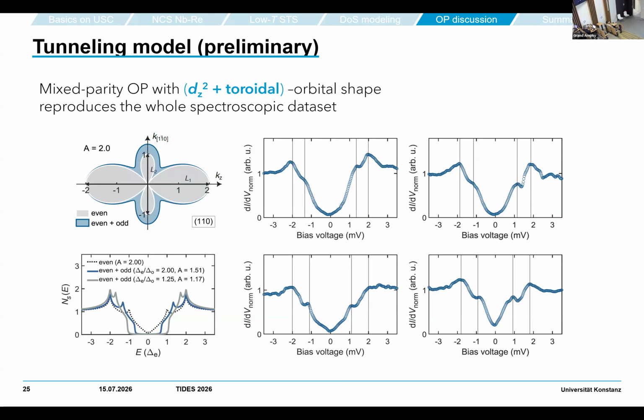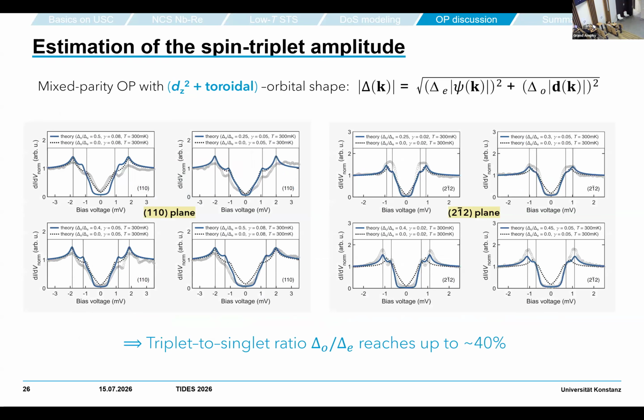We can also try to fit this. This is done here for the 110 plane, exactly what I just showed. It's not a perfect fit, but a reasonable agreement. As another example, on this 2 1 bar 2 plane, where we saw interesting spectra, we can also qualitatively describe the zoo that we observe.